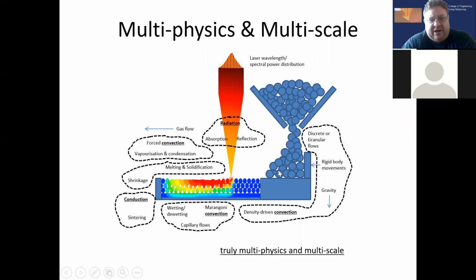And then we've got the discrete nature of the powders as it tumbles down from the hopper and is spread across the plate with rigid body movements of the wiper. This causes a segregation of particles. Typically small ones go to the bottom and larger particles rise to the top as they're driven across. So it's almost counterintuitive, but this will cause a segregation of particle sizes, which itself will then have an effect on things like porosity. So there's a lot of physics going on, and it's on a lot of different scales.